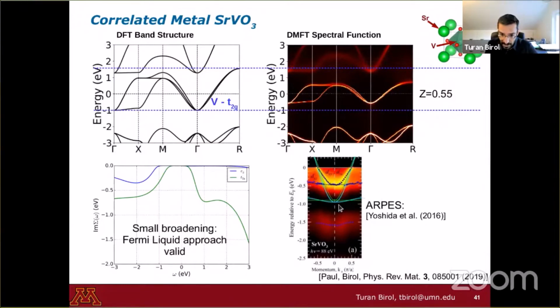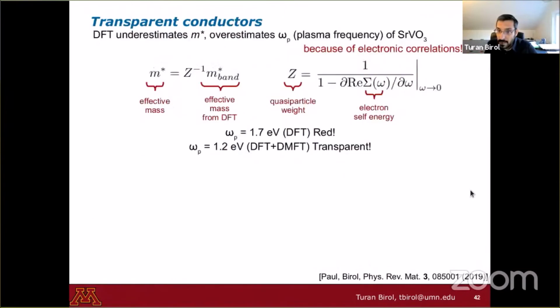So here the green line is DFT. This is from an earlier work of someone else, whereas the background is ARPES, what you see in the experiment. And as you see, the ARPES data is just half as wide as what DFT predicts, so in line with the DMFT.